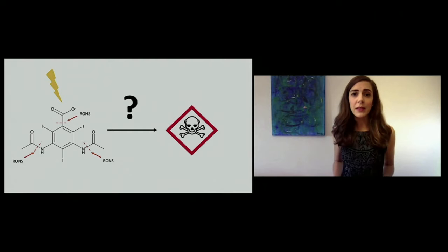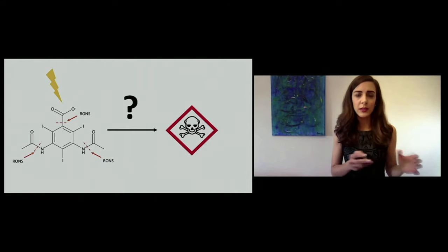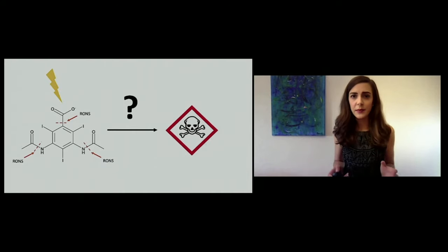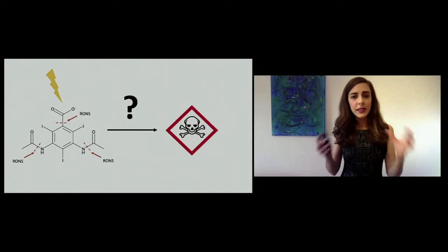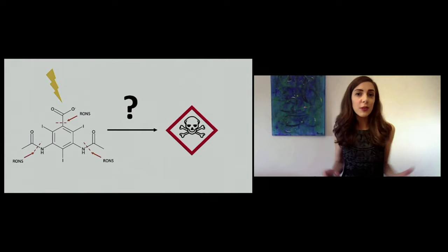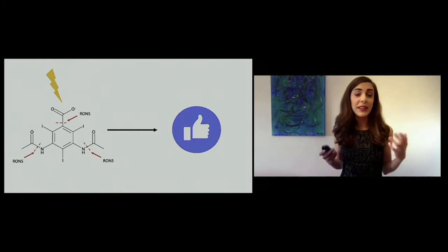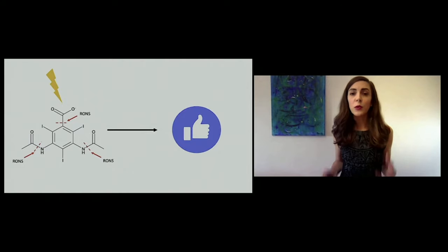So what we did in my lab is that we took this solution of plasma-treated diatrizoate with all the small molecules that we had produced, these broken down pieces, and we did a standard toxicity test, which works with bacteria. And the way it works is that you give the solution containing diatrizoate and the smaller pieces to bacteria. If they survive, it means that it's not toxic. And if the bacteria die, it means that it's toxic. And the good news is that the bacteria survived. And then we were able to prove that what we're producing is not toxic.